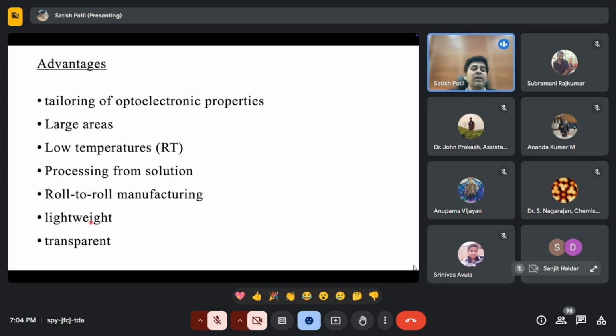Lightweight: I will take one example of organic photovoltaics. These materials have a very high extinction coefficient, so they absorb a lot of light, and you can make a 100 nanometer thin film and make a wonderful device. Whereas silicon is not a very good light harvesting material, so you have to make very thick cells to harvest more light. In this case, you can use a very thin coating of a dye on any surface, with a thickness in the range of 100 to 150 nanometers, to make a very high efficiency device. So overall, the weight of the device is very light compared to the conventional semiconductor.